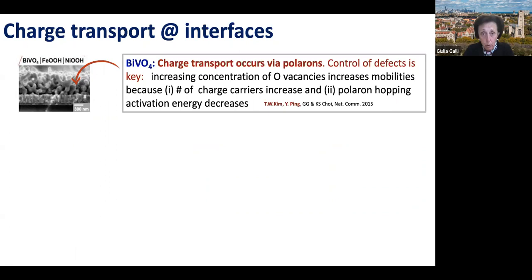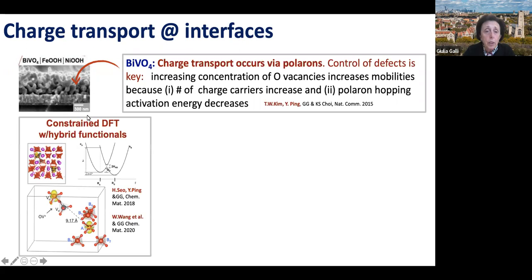Charge transport occurs via polarons. There are charges that are localized due to the interaction with the ions. I already showed you an example with tungsten oxide. For bismuth vanadate, we actually have small polarons. They are very much more localized than in tungsten oxide. So what did we do here? To understand the charge transport, we cannot do this just by straightforward simulation. So we did constrained DFT calculations by adapting Marcus theory to the solid state, and we tried to understand how the polaron hops, looking at the relative hopping probability of the polaron.